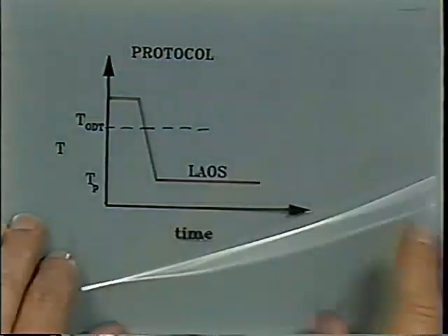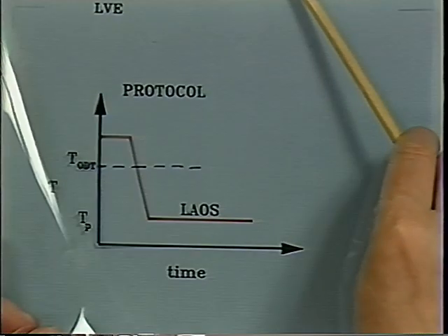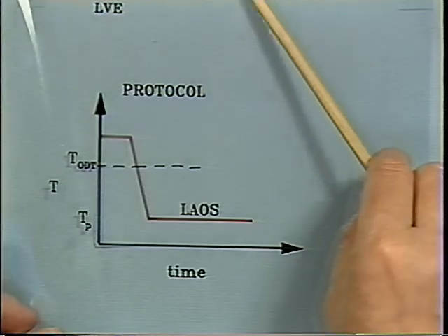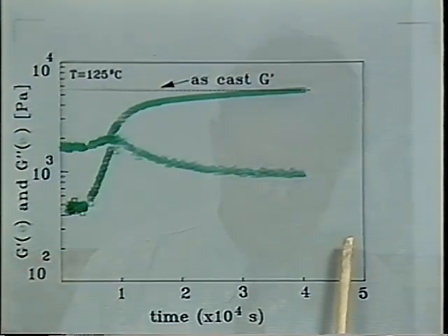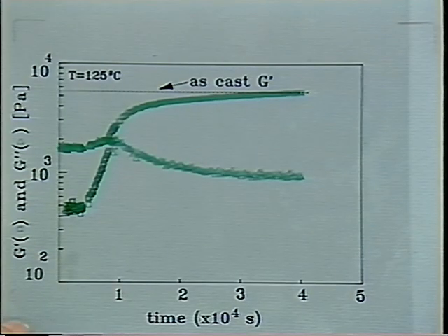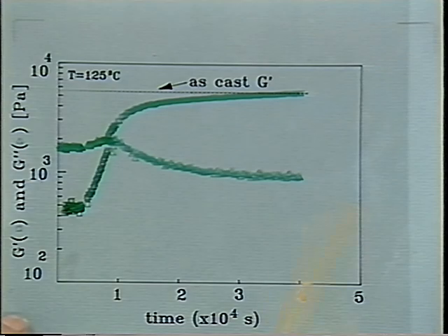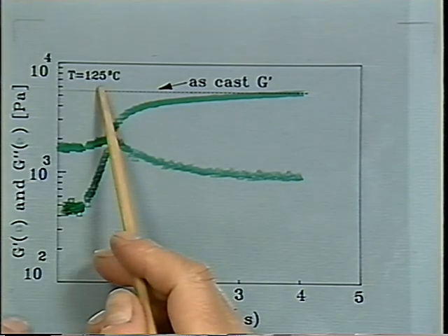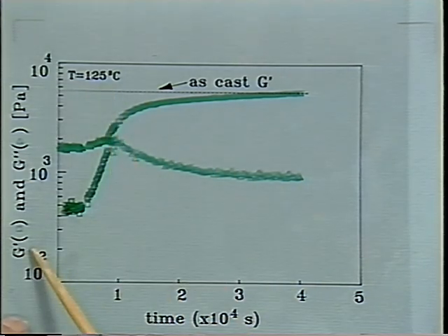And indeed, that's really what's happening. And we do that during the phase separation; we perform that experiment. The quenched sample is probed here, for instance, at one frequency. We just go from a single phase down, quench it to 125 to the phase separated structure, and look at G prime, G double prime.